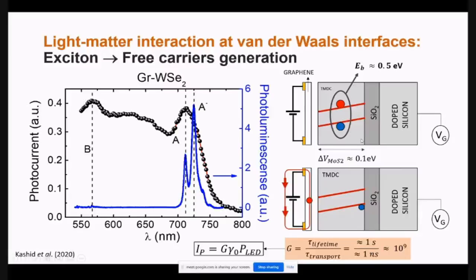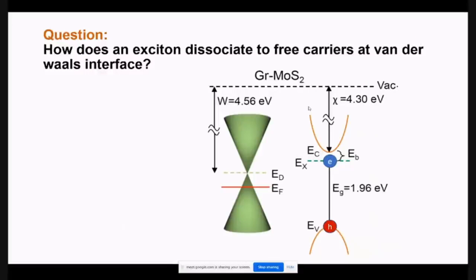Okay. It turns out that it's very easy to understand that this is entirely because of exciton formation in the molybdenum disulfide layer. You can see that when light falls, you create an exciton in the TMDC layer, and then the exciton splits immediately. And you can see that the photocurrent, the black one, is finite only when there are the exciton peaks, only when the energy of the photon is higher than the excitons of the TMDC layer that we are using. So essentially, breaking of the exciton is the reason, or the physics, of this photodetection. However, the question is then, how does an exciton dissociate into free carriers? So it turns out that this is not very difficult.